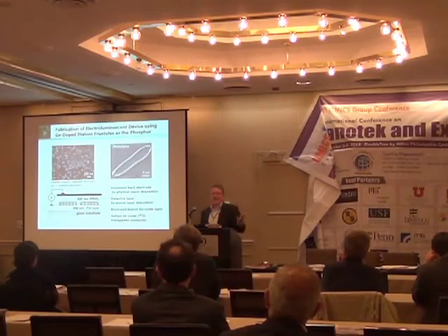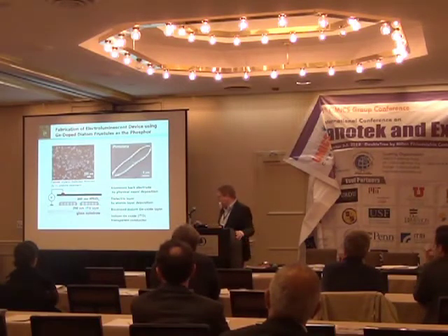And then if you just take that dense film and use, for example, oxygen plasma treatment, you can basically take off all the organic materials, as carbon dioxide, and leave behind the silica shells, in this case on an indium tin oxide conductive glass layer.